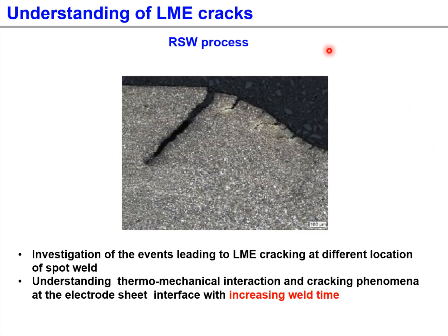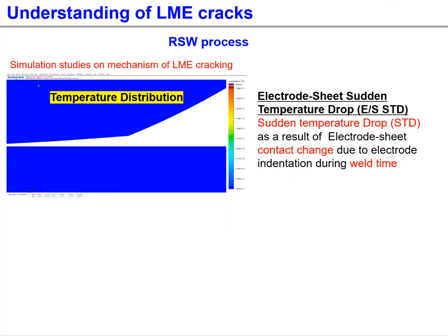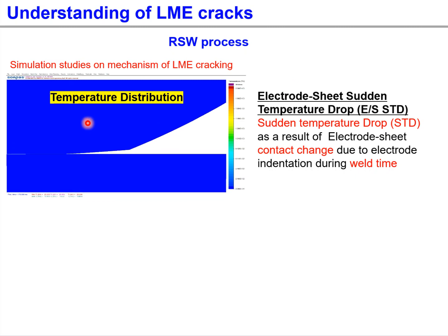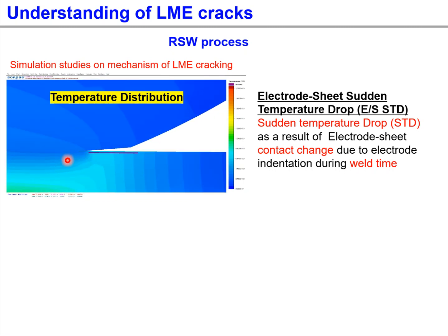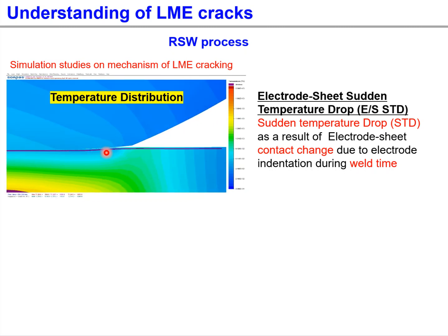To extend the knowledge of the LME cracking mechanism, further studies were carried out on the reasons for LME cracks at different locations of spot welds and differences in LME crack lengths with location. The study was done with a systematic increase in welding time to understand the thermomechanical interaction for LME cracks. When the welding current starts to flow, the temperature of the entire weldment increases. However, the electrode and sheet surface start to make a new contact, which ends up with a sudden temperature drop at the new contact surface, since the electrode is cooled by the coolant.